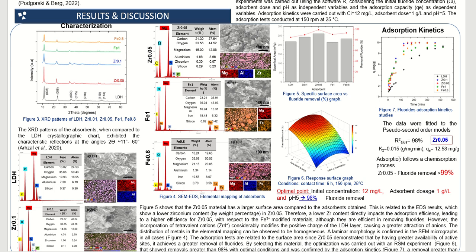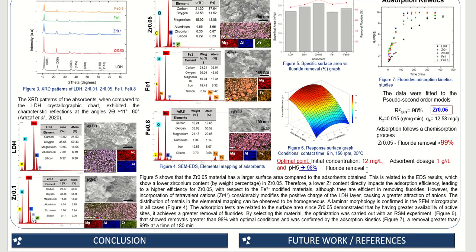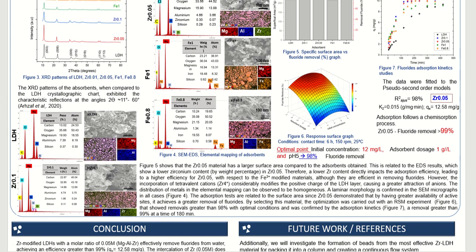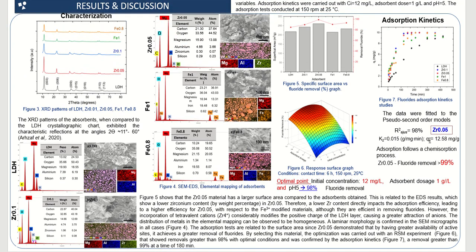Upon finding the most efficient material with good properties, the optimization process continued, for which an experimental design was carried out. Figure 6, where the optimal adsorption conditions were an initial fluoride concentration of 12 milligrams per liter, an adsorbent dose of 1 gram per liter, and a pH of 5. 98% removal was achieved with an adsorption capacity of 12.58 milligrams per gram. Then the equilibrium time was studied by means of adsorption kinetics, figure 7, where at 180 minutes,